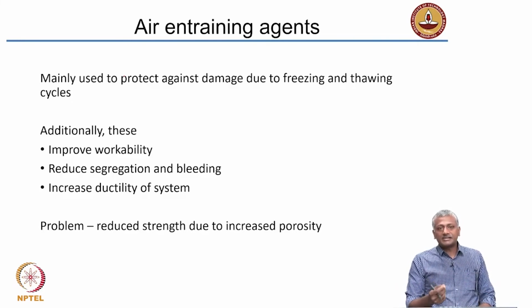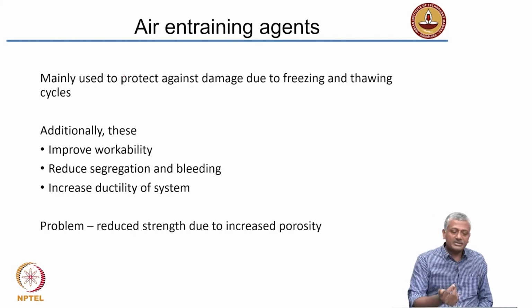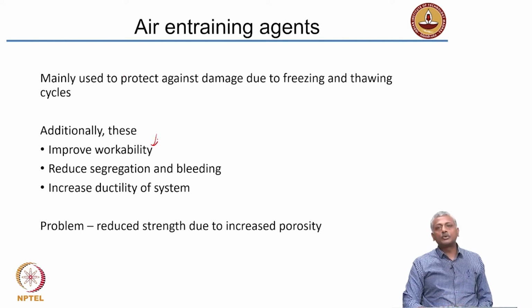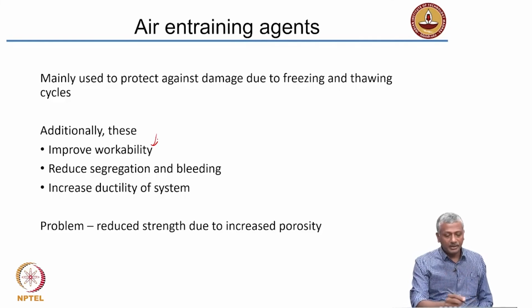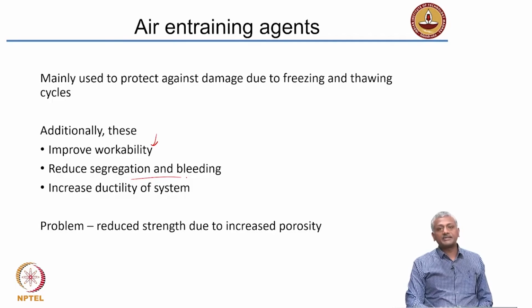So, in such cases, what we do is we put very small air bubbles in the concrete. Air entraining agents create small air bubbles in the concrete that provide a space for the water to convert to ice and expand. So, that reduces the stress in the concrete and reduces the cracking. Freeze thaw is a major problem in certain parts of the world, and that is where air entraining agents can help. Sometimes they also lead to additional benefits like improving the workability, reducing segregation and bleeding, and increasing ductility of the system.